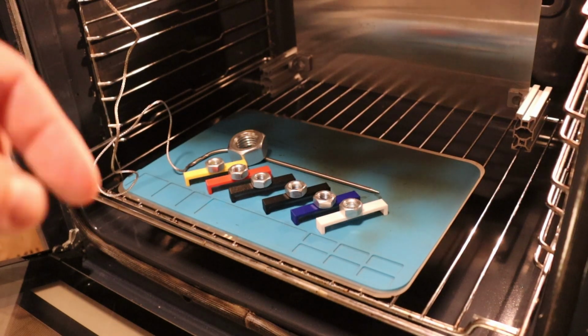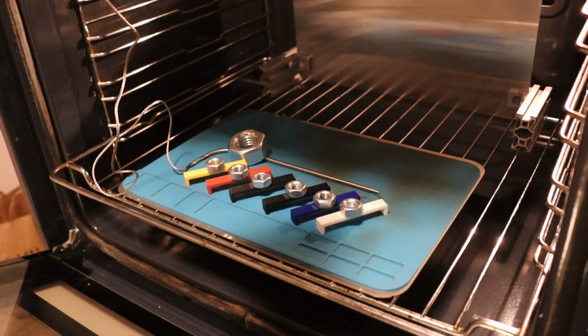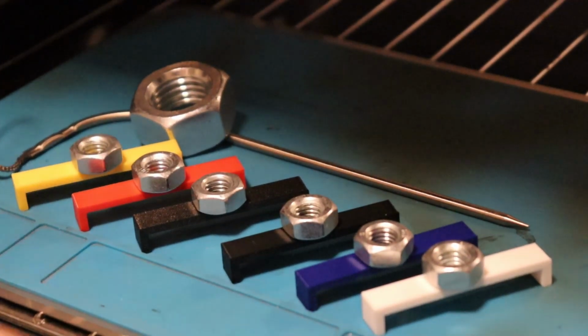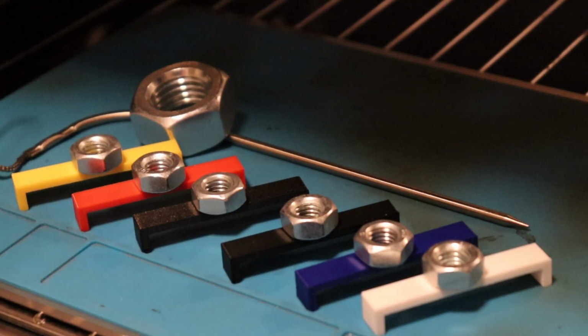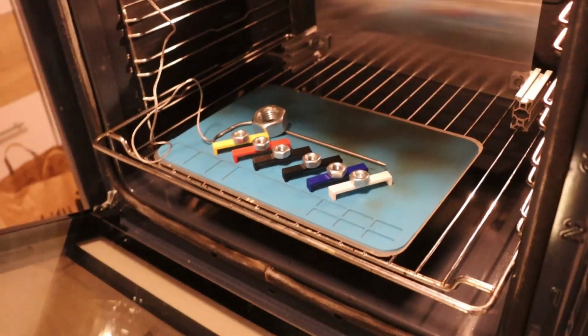The temperature test in the oven, and this is the sensor. And these three on the right side are those filaments from this video. M10 nut is a small load, and I want to record the temperature of the first deformation. This is a sped up time lapse video. And all three started to deform at similar temperatures, approximately at 90 degrees Celsius.